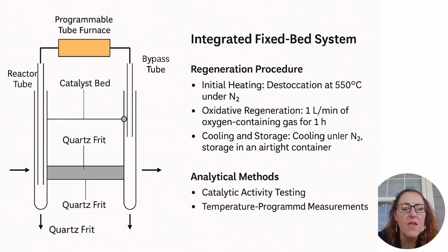In this study, an integrated fixed-bed reactor system was built to allow the oxidative regeneration process for the spent catalyst samples and the catalytic activity evaluation process for the newly regenerated catalysts. The fixed-bed reactor system was constructed using high-purity quartz components to prevent contamination and withstand elevated temperatures. The reactor assembly consisted of two parallel quartz tubes enclosed within a programmable tube furnace.